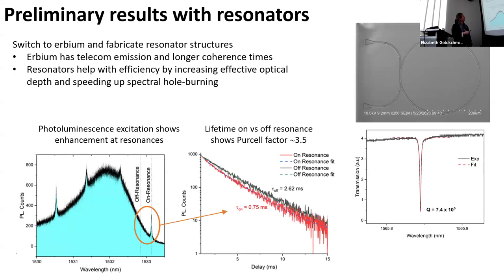And so we can do photoluminescence excitation here. So now we're sending in light and we're looking at the emission that comes out. This wide thing here is the erbium peak. So this is everywhere where there's erbium. There's also erbium in the bus waveguide, right? And so we're going to get emission, whether or not we're on a resonance. These peaks, though, are the cavity resonances. So we get even more erbium emission when we hit the cavity resonance.